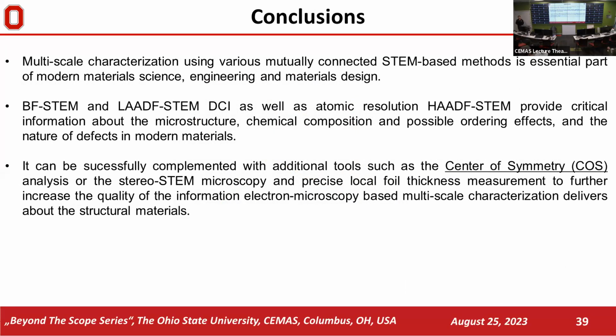Multi-scale characterization using various mutually connected STEM-based methods is an essential part of modern materials science, engineering, and materials design. STEM-based diffraction contrast methods, as well as atomic resolution STEM, provide critical information about microstructure, chemical composition, possible ordering effects, and the nature of defects in modern materials. And it can be successfully complemented with additional tools, center of symmetry or stereo STEM microscopy, and precise local foil thickness measurements to further increase the quality of information.